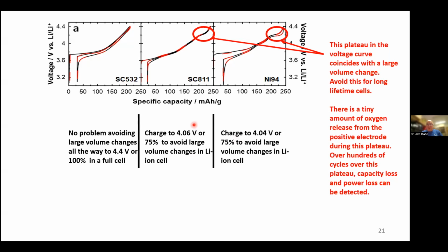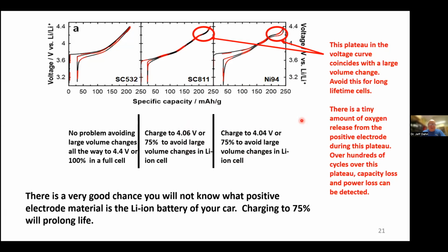So if you have a long-range electric vehicle, chances are it has one of these high nickel content materials, and if you charge to 75%, you'll avoid this large volume change and this tiny oxygen release. So there's a really good chance you're not going to know what the positive electrode material is in the lithium-ion battery of your car. So you can just say, oh, well, I don't know, but I want to be safe, so I'm going to charge to 75% most of the time.